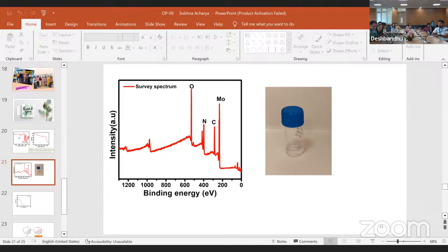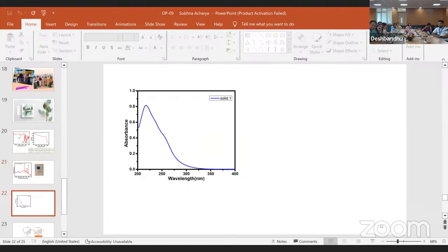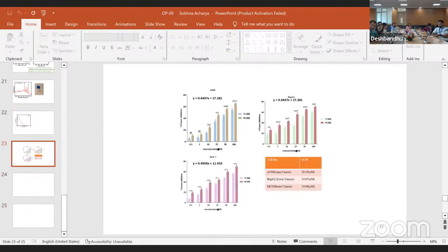Yes, sir. It's a programmed hot air oven, temperature programmed. We just have to set the temperature and the time. Then the reaction will occur and we are getting the white crystals. This reaction, you can carry it out in normal atmospheric conditions? Yes, sir. 140 degrees Celsius, 48 hours. Fine. But what about the atmosphere? Was it nitrogen? No, sir, room temperature. Nothing like that. Room temperature. Right.